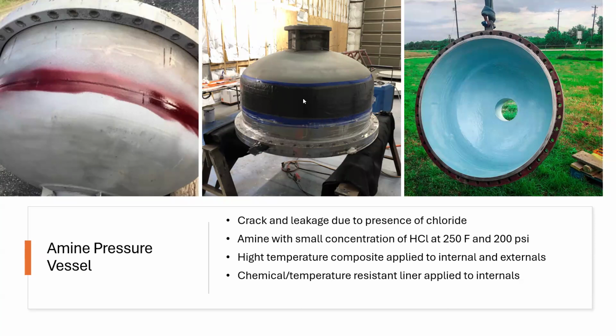So here, since we had a crack and through wall defect and leaking and high pressure, we did a composite repair on the outside and a composite repair on the inside. Once the composite repairs were installed, we sweep blast everything and apply a two coat system that can handle the chemicals at the temperature and pressure. So the composite is to give it structure, to give it leak tightness and hoop strength. And then the coating is to protect the composite and protect the metal from further degradation.